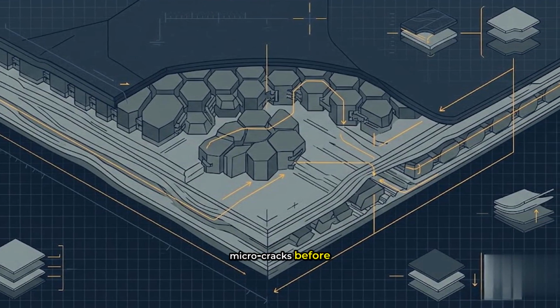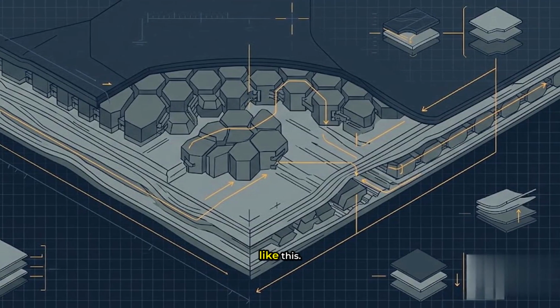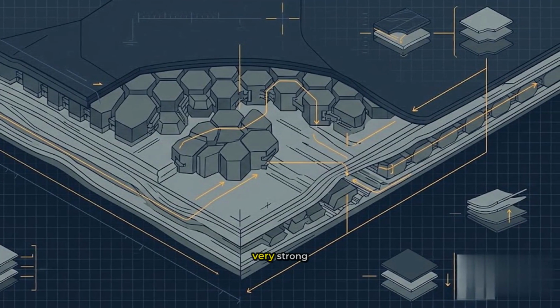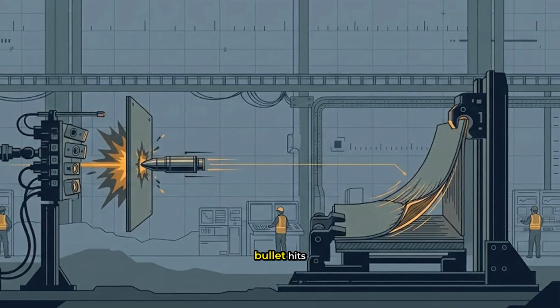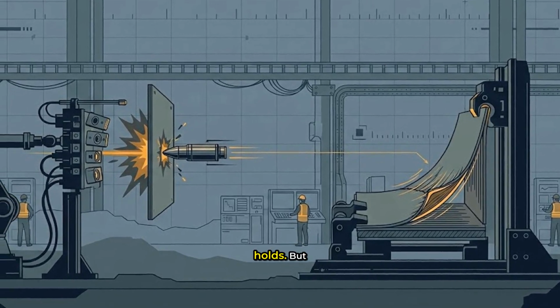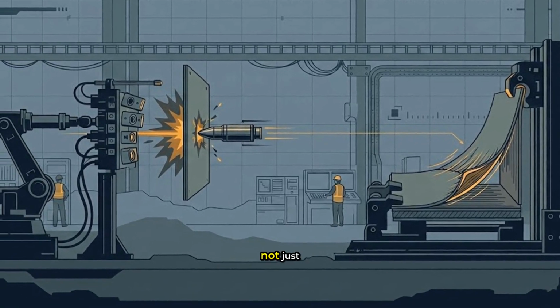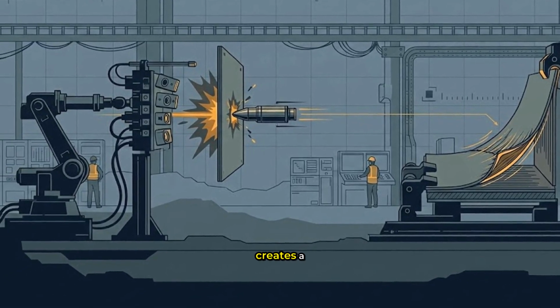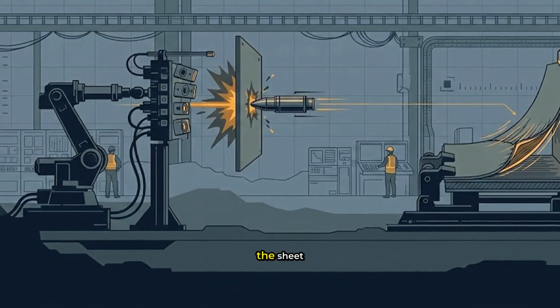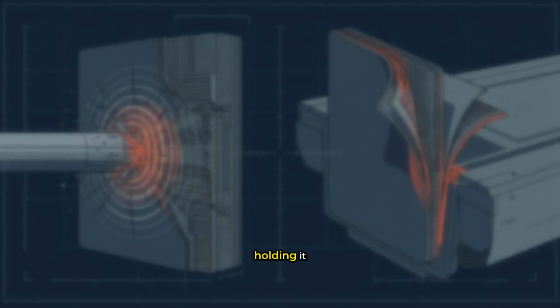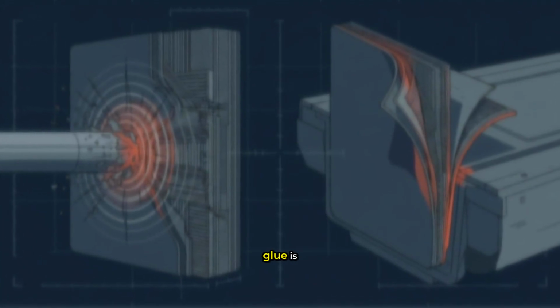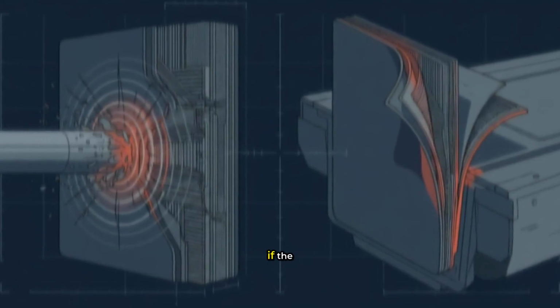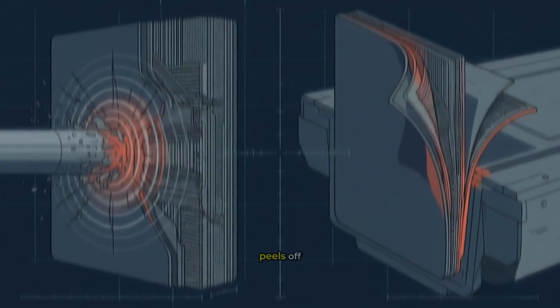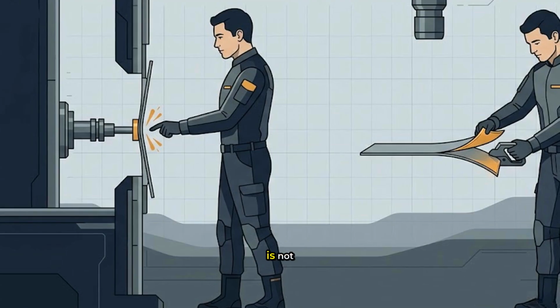Think of it like this. Graphene alone is a very strong sheet of paper. A bullet hits it and the sheet holds. But a bullet at an angle does not just push, it drags. It creates a tearing force that pulls the sheet away from the glue holding it to the structure. The glue is the polymer matrix. And if the matrix fails, the graphene peels off like a decal. That is not bulletproof. That is a failure mode that lab impact tests rarely capture.